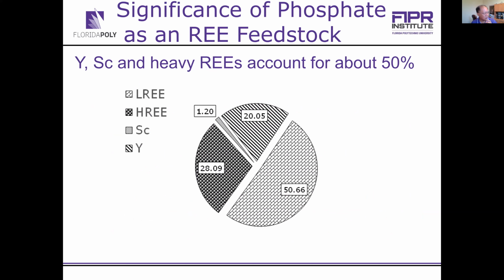Why do we think this is significant? The rare earth elements in phosphate: first, the rare earth elements in Florida phosphate contain close to 50% yttrium and heavy rare earth elements. And these are the more critical rare earth elements. We ran this on almost every stream. So roughly it's 50%, some maybe 49%, some 52%. But 50% is a good number in terms of yttrium and the heavy rare earth content in the Florida rare earth elements.